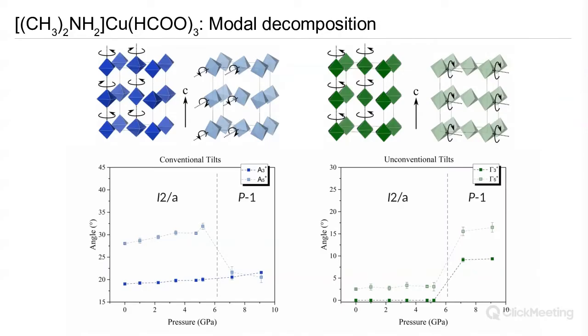So the approach that we took to try to understand what's happening at the level of the structure is to perform a modal decomposition of both structures with respect to some hypothetical high symmetry parent. What this means is that we take a high temperature structure where, for example, all of the octahedra are cubic, they are all upright and well aligned. In this particular case, this would have been in a tetragonal symmetry. And then we can do a decomposition of the true structure in terms of the amplitudes of these modes. And these are symmetry adapted modes that are allowed within the symmetry in question. And what we plot then is the evolution of these modes as a function of pressure.